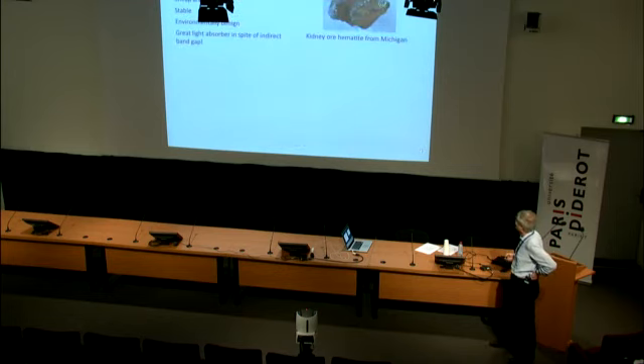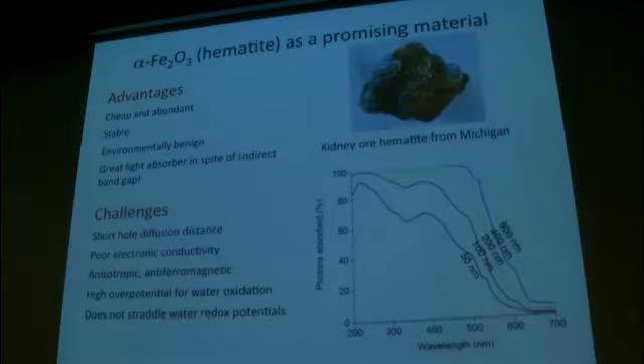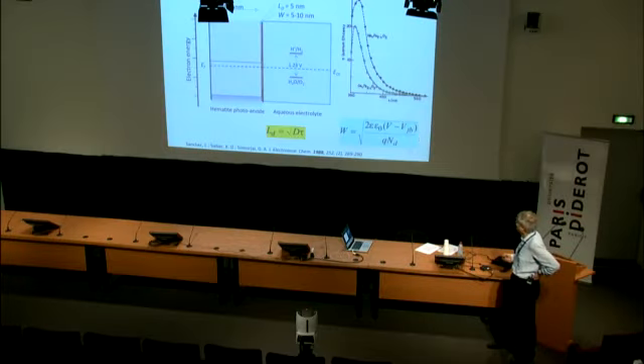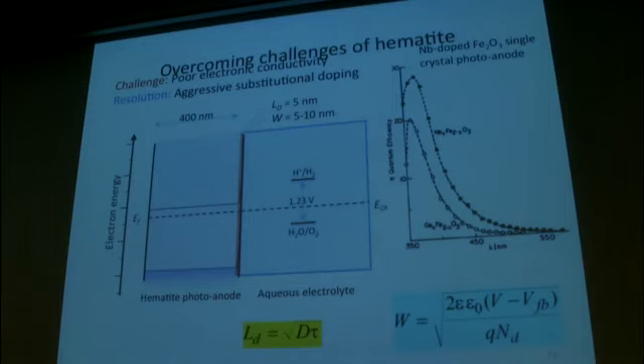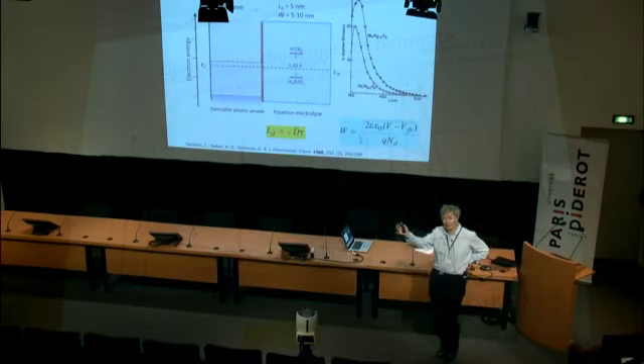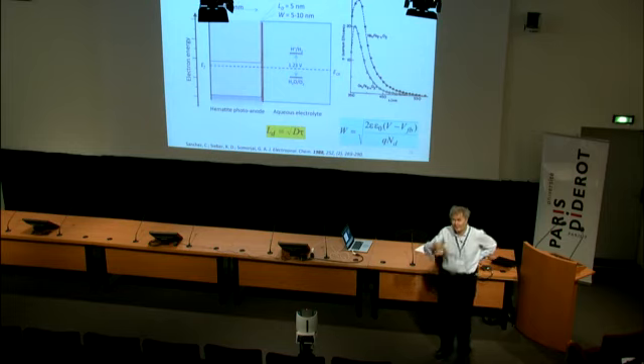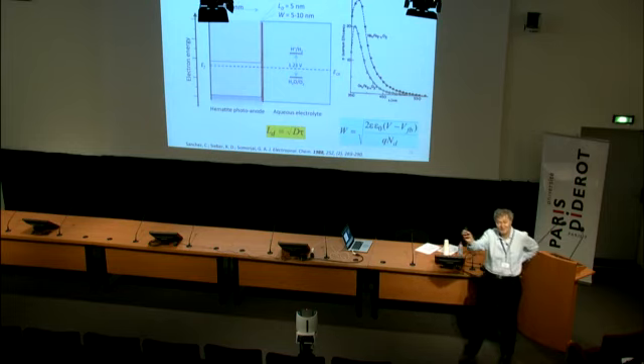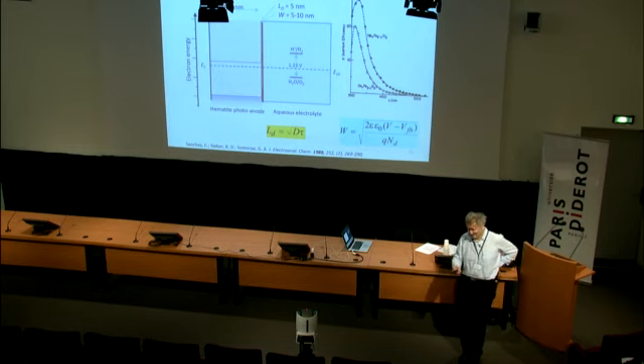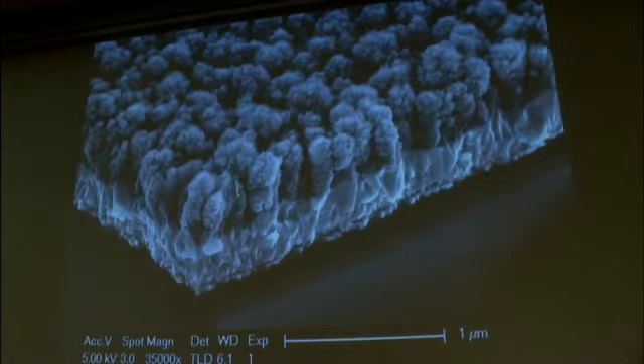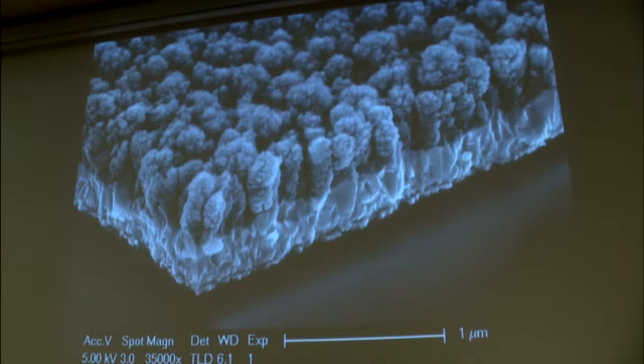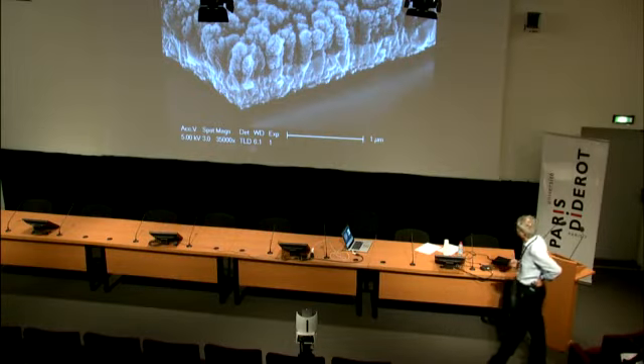Persistency has paid off. And so hematite is, of course, a very cheap material. It has a problem with short hole diffusion distance. These are all problems, but you can deal with those problems. In a single crystal, only the very thin layer, the first nanometers, works, because the hole diffusion length is a few nanometers. The optical absorption length is a few hundred nanometers, so you collect only from a few nanometers. It's not a good proposition. But with these cauliflower structures, we have nano-sized features, and so you get to a point where you collect the carriers they produce within those cauliflower structures.